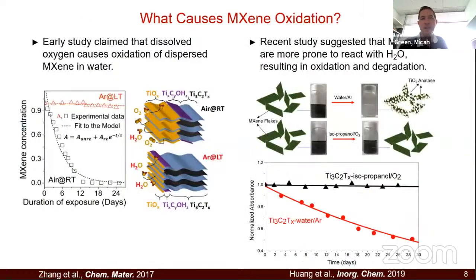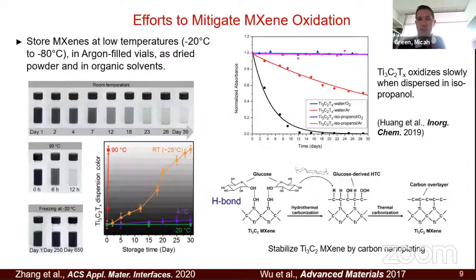Our group has done a lot in this regard. There's actually a little bit of controversy on what causes oxidation. Some early papers had claimed that it was dissolved oxygen in the water. And frankly, I don't believe that. There's not enough oxygen in the water to do that. It's more likely that it is indeed the actual water that interacts. And that's been shown even more recently.